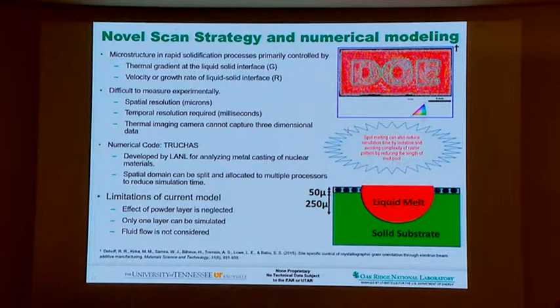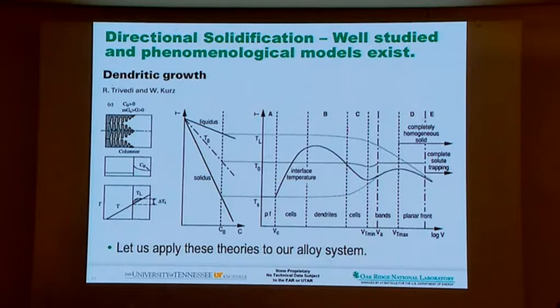And then he said the next thing is, since we are doing quite a lot of transient analysis, I'm going to throw away my fluid dynamics, and only do transient heat transfer analysis. This is similar to putting a small heat source on the top of a substrate and then seeing how the melt pool collapses. That's what he did. Why is he doing that? If he knows the thermal gradient, G, and the liquid-solid interface velocity, R, he can actually predict what is happening in the solidification. I'm going to walk you through this for my metallurgy friends here.